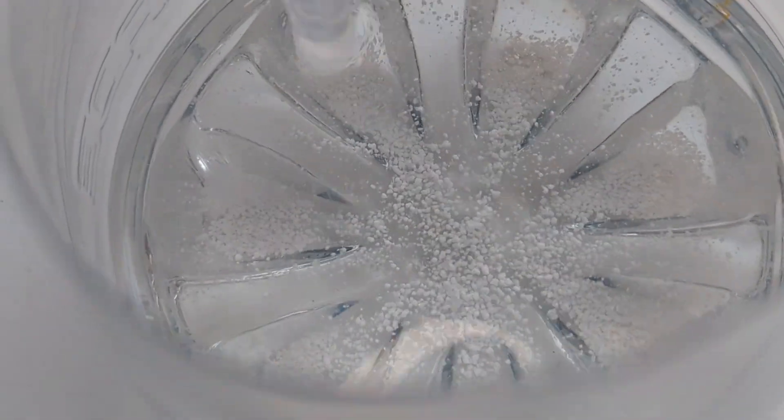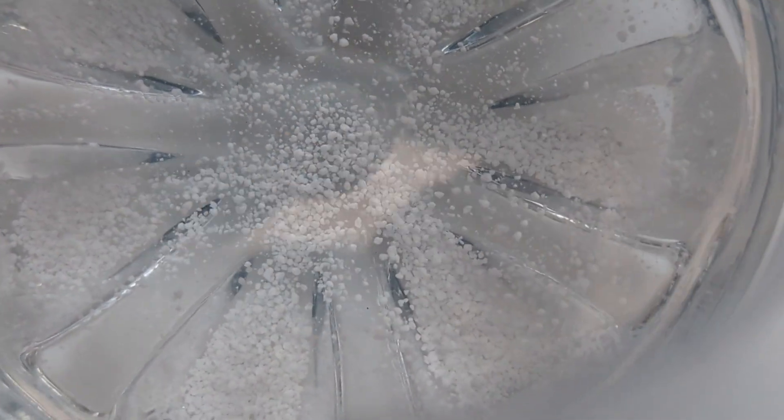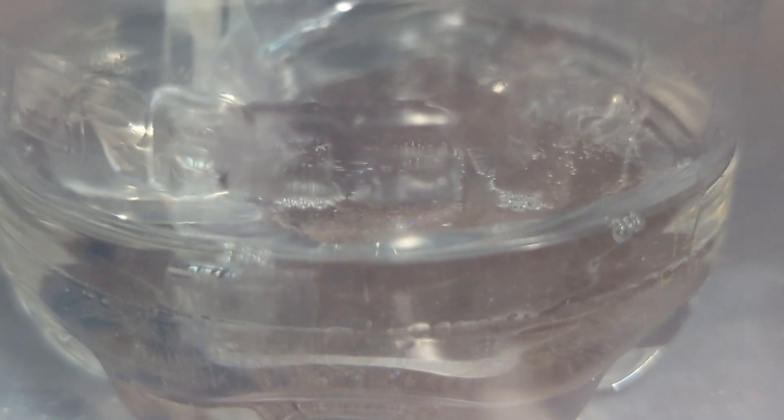But just let it sit. Let it sit for a day. Let it sit longer if you need to. This one seemed to be fine after about six hours. And then it's pretty much ready to go. Just give it one last little mix. Drop your stone into it. And then we're going to chuck it in the vacuum chamber and pump it down.